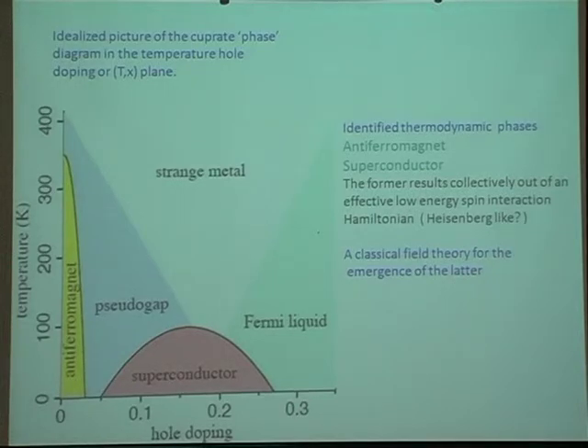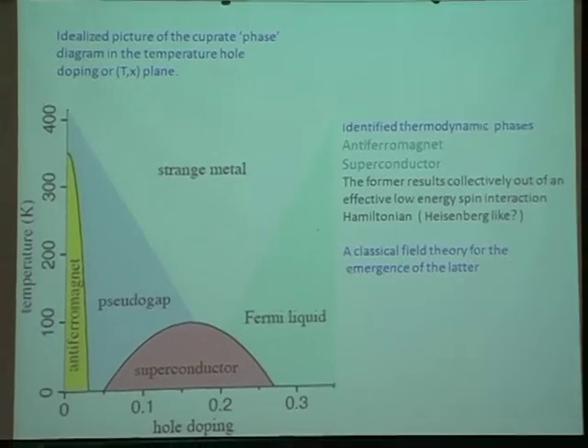Can this be done if you start with, say, this free energy, like some kind of alpha m square plus? Yeah, that is the obvious possibility. If you stay phenomenological, the obvious possibility is that you put a term like Si dot Sj in the free energy functional, then couple this to the Cooper pair degrees of freedom, and then run it and see what happens.